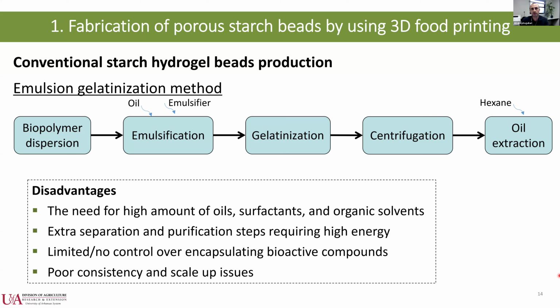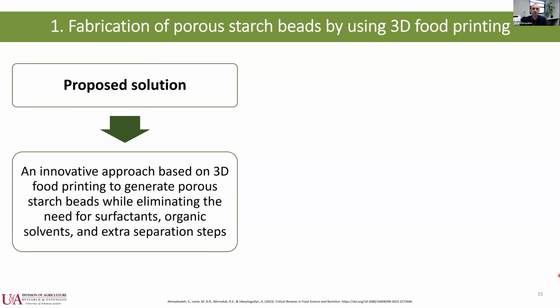So there are a lot of disadvantages and limitations with this protocol. You really need a lot of oil, emulsifiers, and then you need to use an organic solvent to be able to extract them back. There are a lot of extraction and purification steps that go into this process, which requires a lot of energy. Another limitation is you do not really have control over where you locate your bioactive compound, and there are issues with scale up because of that. So our proposed approach is to really eliminate the use of oils, emulsifiers, and toxic solvents in the process to generate starch particles or beads using 3D food printing.